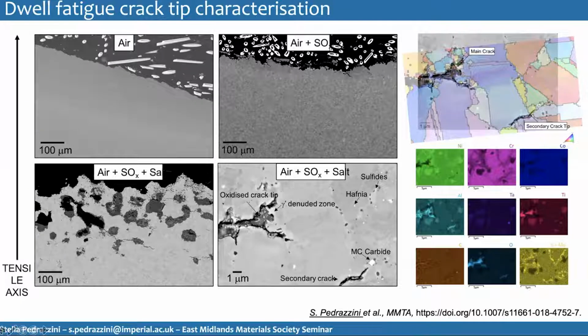And then adding salt, it's flat again, but there are 45-degree cracks and oxidized corroded cracks going all the way down into about 300-400 microns into the sample. And this crack, zooming into that one, this is what this picture is. We can see an oxidized secondary crack with a lot of different particles that have formed around it. Now, EBSD overlaid on top of this same image tells us that the crack has gone along the grain boundaries, and the secondary crack as well have gone along grain boundaries in this case.